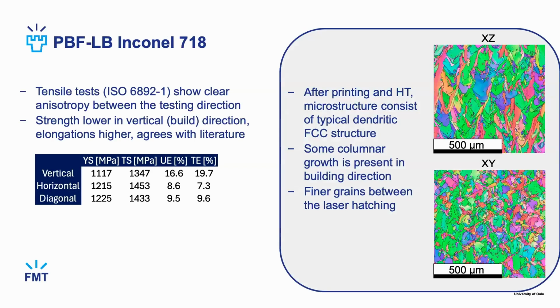So about the material itself. If we look at the static properties here, we can see that there is a clear anisotropy between the testing directions. Strength is lower in this vertical direction that we studied in the fatigue, but the elongations are higher, and this agrees with the literature.